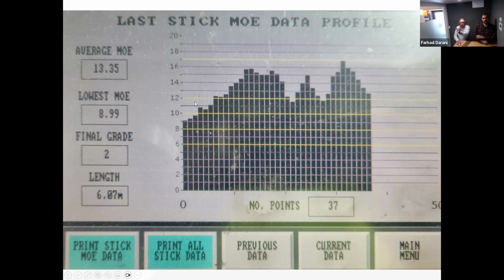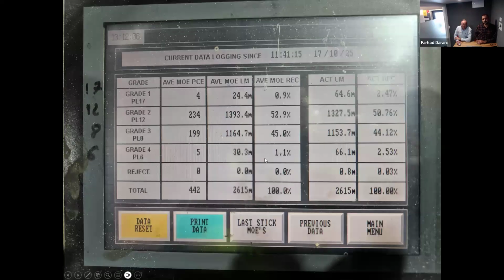So we cut out portions of that lumber: everything above 11.5 would go into SG 12, and then we'd pull some 10 out, and then there'd be some 8. Over the average of a run, on this one here, we're getting 52.9% SG 12, 45% SG 8, 1.1% SG 6, and a tiny wee bit of SG 17.